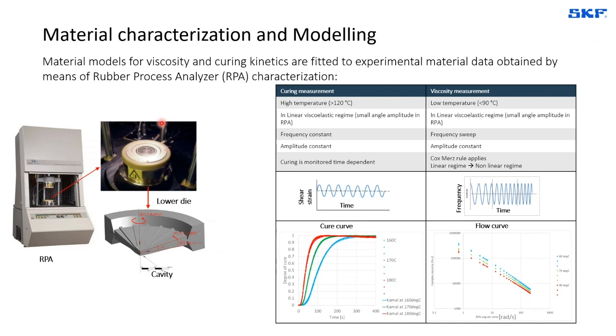So what we do is we use a rubber process analyzer in different conditions, either at constant frequency and constant amplitude of shear, over a certain duration of time at a given fixed high temperature, in order to understand the curing kinetics and how the thermosetting is activated in the rubber material. We also use the same equipment, but in a different setup, where we change the frequency, corresponding to the shear rate, in order to understand the evolution of the viscosity over a shear rate range.